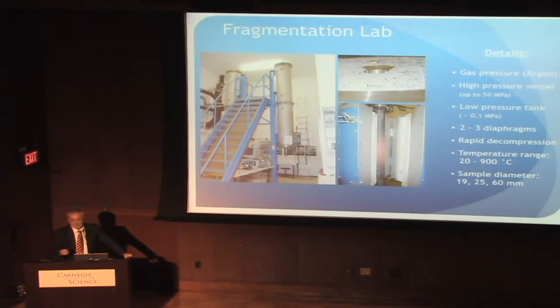What is the driving force for the failure then? We have bubbles, gas bubbles, with high pressure gas in them in the sample, as we do in magma. And once you take away the confining pressure, you still have all of the vesicular pressure stuck in the sample. And these bubbles can be as finely distributed as Coke when you shake it up. Every single one of those bubbles wants to blow because it has more pressure on the inside than is sustained on the outside. And they do.